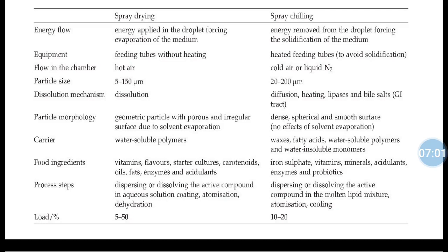The release mechanism of spray drying products is dissolution, whereas in spray chilling it is diffusion, heating, lipase or bile salts. Particle morphology in spray drying is a geometric particle with porous and irregular surface due to solvent evaporation, whereas in spray chilling, it is dense, spherical and smooth due to solidification of the core material.